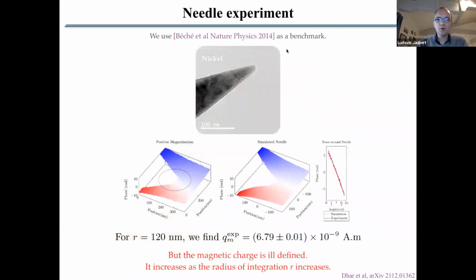So now, first we're going to benchmark our work with the previous work of Béché and collaborators, which was published in Nature Physics 2014, where they did this experiment with a tip of a magnetized nickel sample. So you see you have a nickel, which is magnetized. You look at the really tip, very thin tip of that. And locally, this can be seen as a kind of North Pole here, and the South Pole being projected far away outside of the window of measurement.